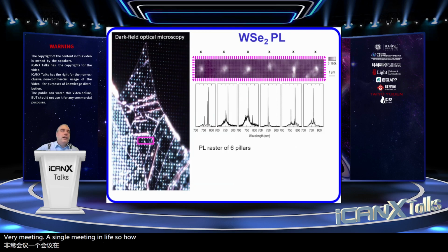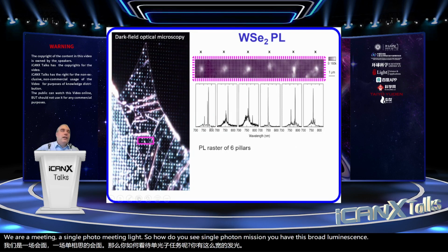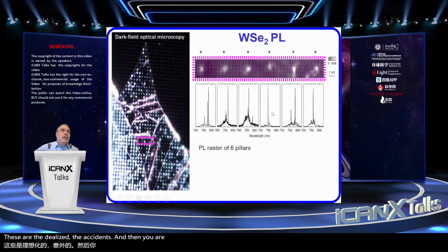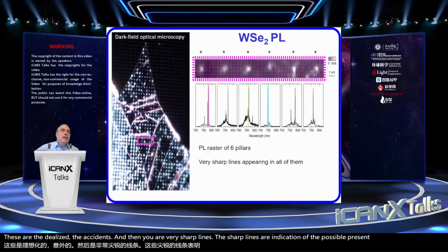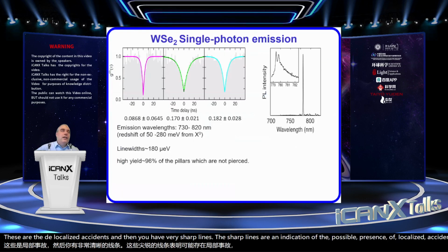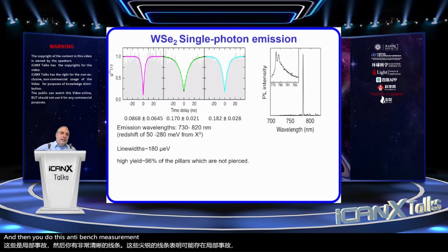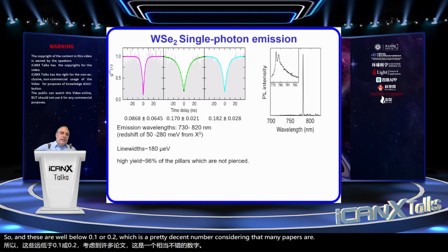So how do you see single photon emission? You have this broad luminescence. These are the delocalized excitons, and then you have very sharp lines. These sharp lines are an indication of the possible presence of localized excitons. And then you do these anti-bunching measurements, these G2 measurements, and you want them to be as small as possible. And these are well below 0.1 or 0.2, which is a pretty decent number, considering that many papers are just publishing with 0.5.